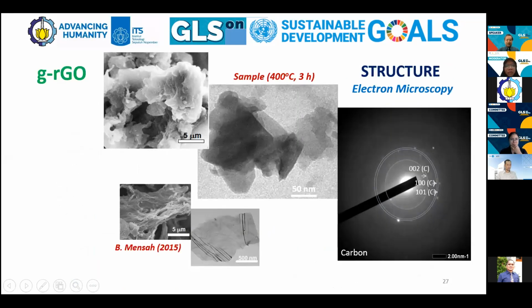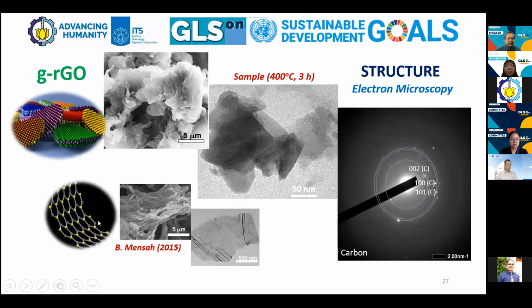Okay, the microscopy of this carbon compound, according to the SEM and TEM, shows the sample looks like a sheet, even though it has not been found in a thin layer, suggesting a graphene compound. It can be concluded at this point that the graphene-like sheet consists of several layers, as illustrated like this. It is a single layer graphene. There are several layers and thicker graphene layers. And our sample is considered to be still like this and not yet like this.